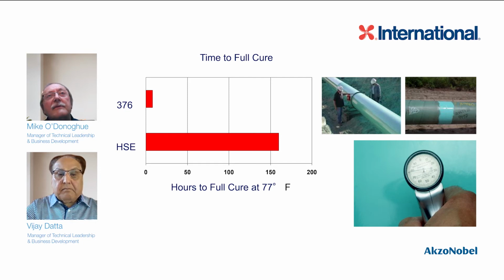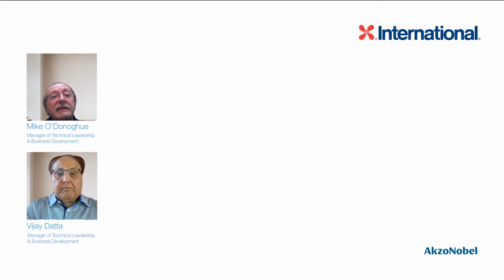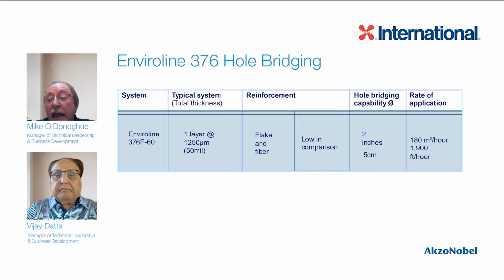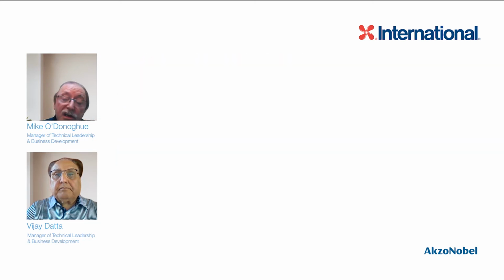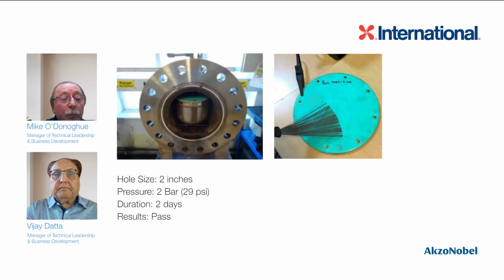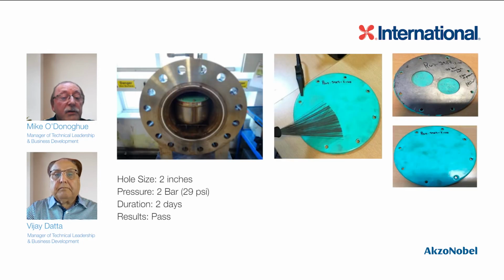Then, if we think in terms of a tank where we've got a flexing bottom, if we ever get a situation where that tank, even though it's flexing, has a perforation in the tank floor, then if you have 376 in that tank, you can actually get hole bridging for a certain amount of time, with the coating being on the tank floor. What we do there is test that and prove it. If the hole size on the tank floor is about 2 inches, and we apply pressure of about 2 bar on the coating over that 2 inches, as you see in some of these slides, you'll notice that the coating has withstood and sustained that pressure, so it hasn't broken. So this is a very interesting aspect of the 376 performance.